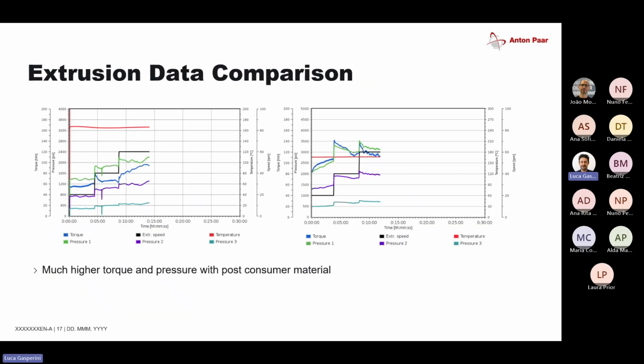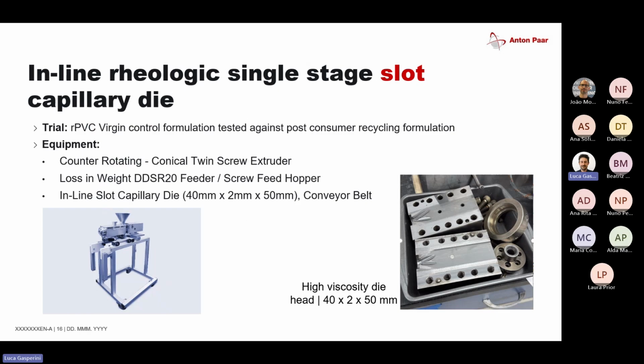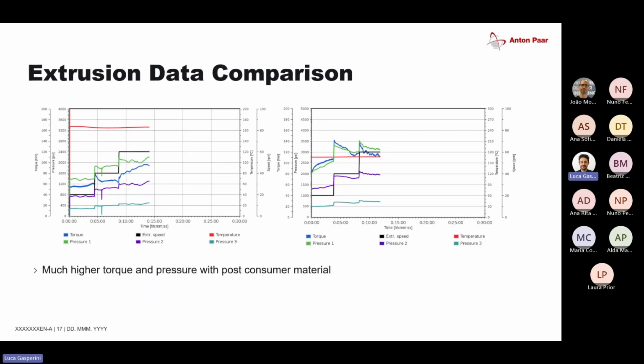So how does it look? Here we were comparing a recycled PVC with a virgin PVC material. And this is how a measurement could look. Usually you do 3 measurements at 3 different screw speeds. For this specific example, it could be seen that for the recycled PVC we had a much higher torque level in the end, which also resulted in a higher viscosity.